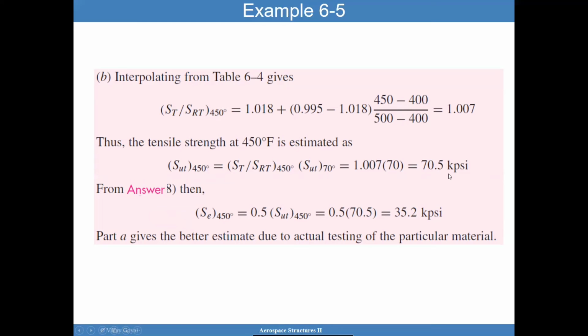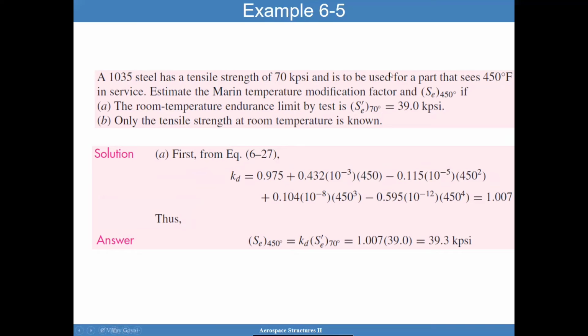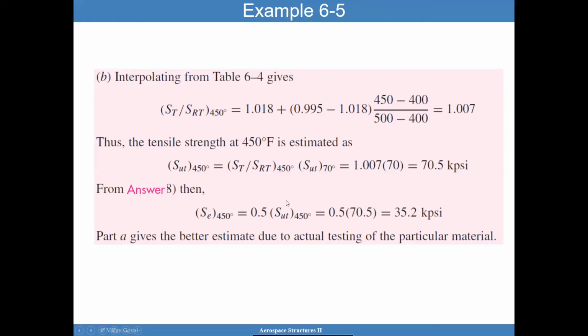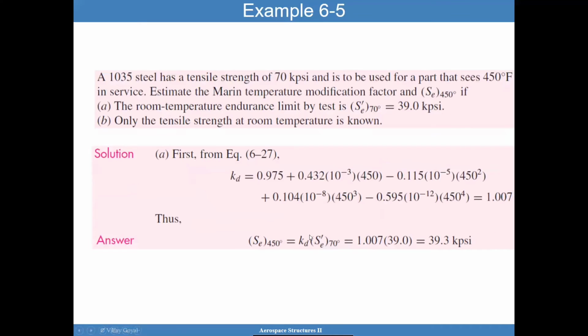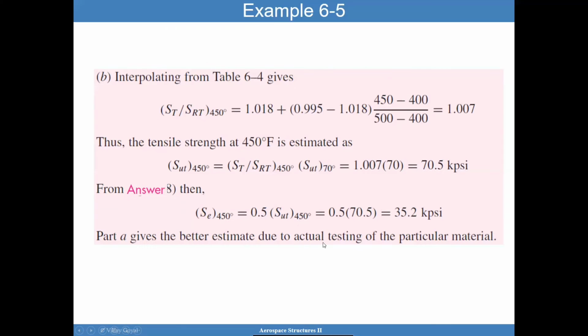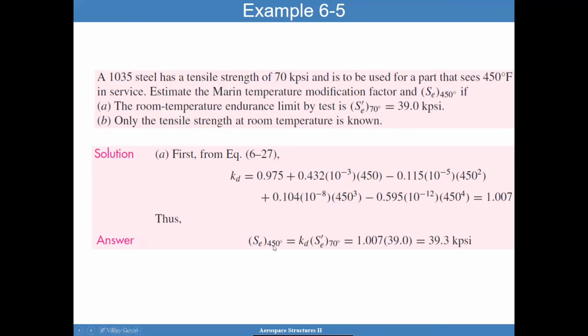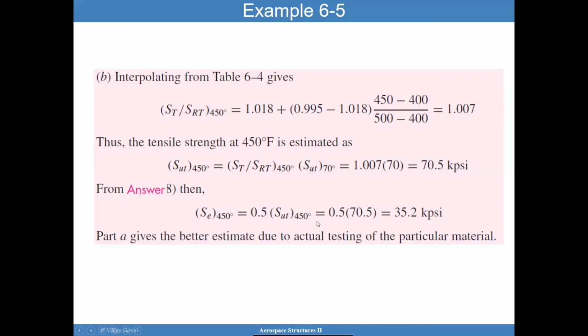And so then you want to calculate for this particular steel. Since you have the ultimate strength and you don't have the value of SE from the coupon, you multiply by 0.5 to then get the 35.2. But this is a better estimate because we got the measurement SE prime directly from the testing. While here, I only knew the tensile strength. Here, I knew SE prime, so I can directly use it. This was a little more conservative.